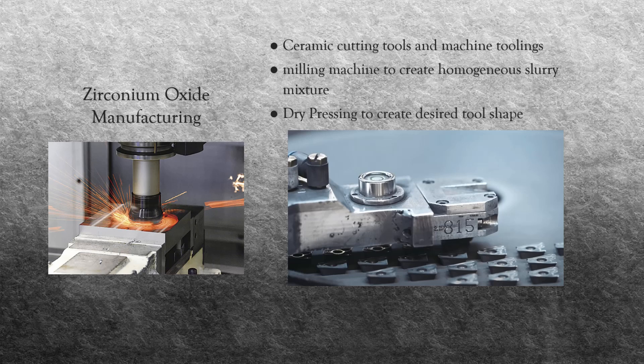Aluminum oxide can also be added to help strengthen and improve toughness in a 1 to 5 ratio. The slurry mixture is then dried using a spray dryer, which rapidly dries the slurry into a powder using hot gases to evaporate any remaining liquid. The resulting powder is inspected before being placed in a storage bin for upcoming productions. A dry pressing machine then feeds the powder into a die that holds the desired tooling shape, where it is pressed using almost 12,000 pounds of pressure. The organic binder helps hold the shape after pressing, and the tooling is then weighed and visually inspected for impurities.